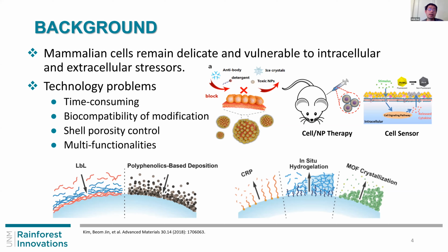Another thing is that they directly use the source to prepare it. So if you want a good structure on the surface, you are limited by the biocompatibility of the source. So a lot of things you cannot use. For example, iron oxide nanoparticles, we can make outside with high temperature, and then load on the surface. But for them, they cannot grow directly onto the cell surface by their technique. So I think we are the first in the scientific area to coat nanoparticles onto the cells.